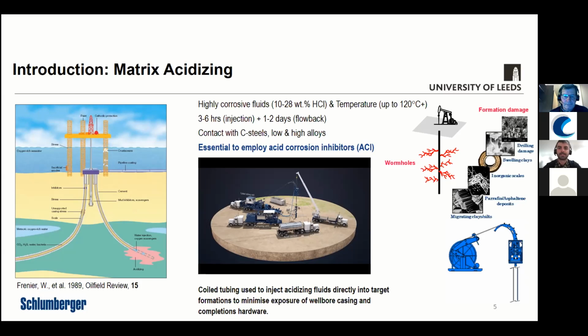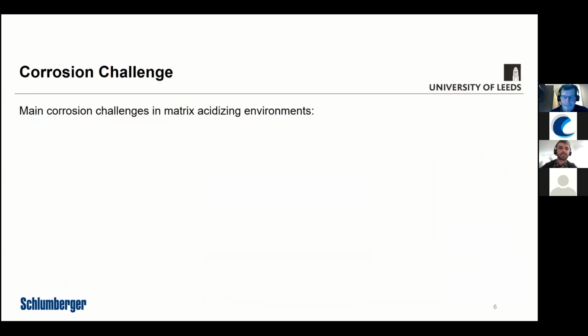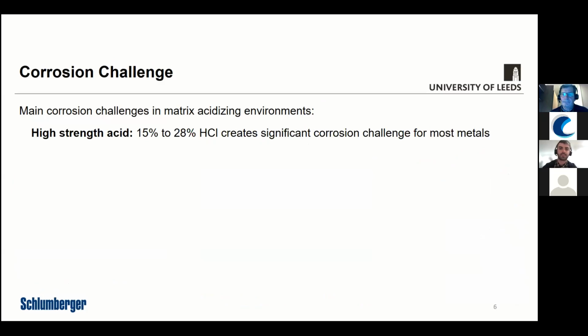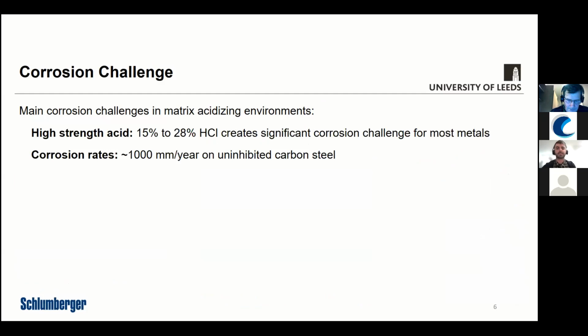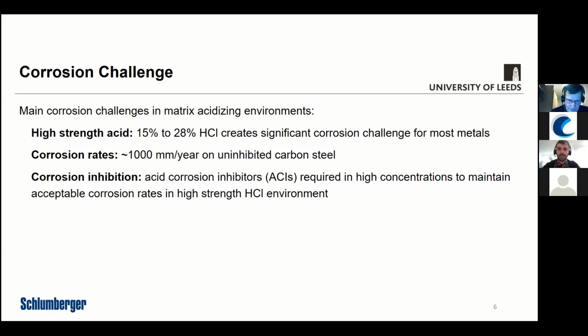So inevitably, when you've got these highly corrosive fluids coming into contact with all the materials in that environment, that can lead to some pretty high corrosion rates. So our main corrosion challenges, like I said, very high strength hydrochloric acid. And just to give you an idea of the corrosion rates that we can get in some cases with an uninhibited carbon steel at the temperatures that would be relevant, corrosion rates can be around 1,000 millimeters per year. So it's huge corrosion rates without the application of a corrosion inhibitor. So obviously, applying an inhibitor is essential. And in this particular case, we would use acid corrosion inhibitors, which are corrosion inhibitors that are ideally suited to the acidic environment. And they're usually required in very high concentrations just to maintain acceptable corrosion rates.